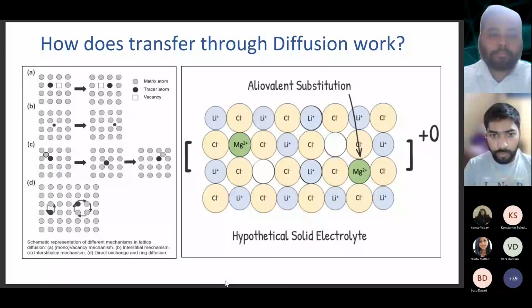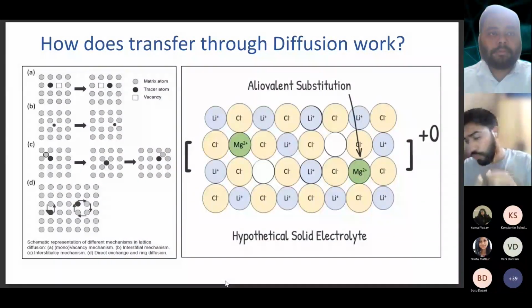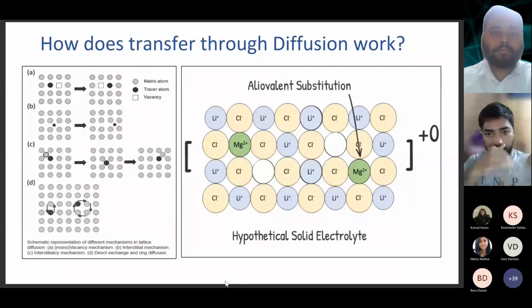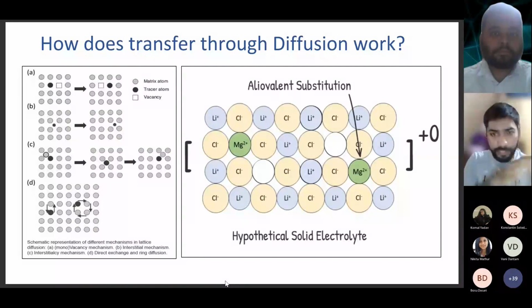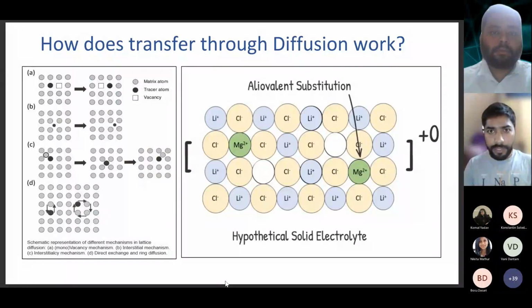Now these two vacant spots are where lithium can be shifted to. So the lithium on the left side can move to the vacant spot, and when one lithium moves to the other part, there's a vacancy created behind. So there's a path for the next lithium to move to that spot and so on. If we have such a vacant defect path, the ions can travel from one end to the other. And this is the way they travel from anode to cathode and cathode to anode. So this is how the transfer of ions is going to work in the case of solid state batteries. Can we move to the next slide?